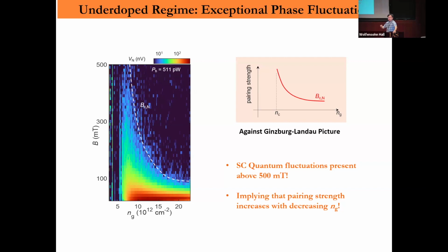And the upper critical field in a superconductor, in this case, can be interpreted as a pairing strength, which means the pairing becomes stronger—the Cooper pairing becomes stronger and stronger when you go to density that's close to critical. This is against Landau-Ginzburg theory, because remember, in the beginning, Landau-Ginzburg theory tells you the pairing strength or order parameter goes down to zero. This is not the case. This is not the Landau-Ginzburg picture. The pairing strength actually goes up very rapidly.